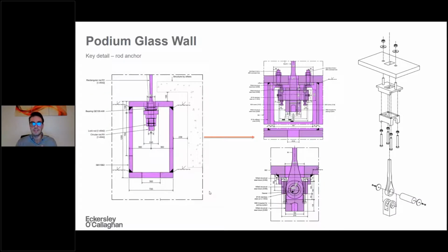One of the other issues was really to design the bottom detail where the rod anchors to the steel beam. Initially we went for a spherical bearing scenario, although because of some issues with the approval authority for the specific product, we swapped to a high-end type of rod, with this kind of fork with a pin. The further issue was to check, with the lateral drift, whether the drift-induced bending stress in the rod was small enough to be absorbed. Luckily, the drift limit for the tower designed by the primary engineer was quite strict, so we had deflection of about height over 800, so about 18 millimeters of lateral drift between top and bottom.